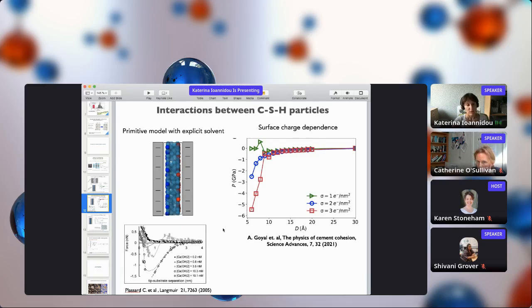We can also reconcile experimental data from atomic force microscopy, where we see that the force measured depends on the calcium concentration and the surface charge, and we can go from a repulsive regime into an attractive regime through this attractive-repulsive interaction.